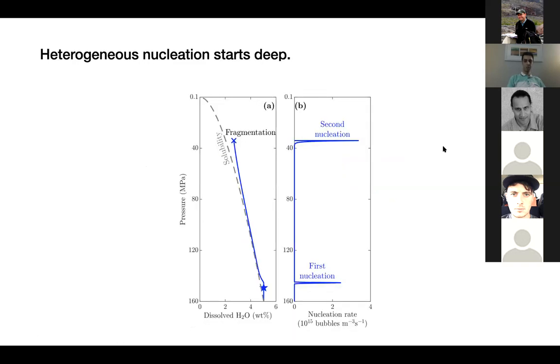nucleation starts deep. Here is a representative example of our simulation results. Magma water is saturated at 160 megapascal. The dashed line here shows the solubility curve of water. As magma starts rising, water becomes supersaturated. In heterogeneous nucleation, nucleation starts at very low supersaturation pressures, shown here at the start. Nucleation rate peaks very sharply and then drops quickly.